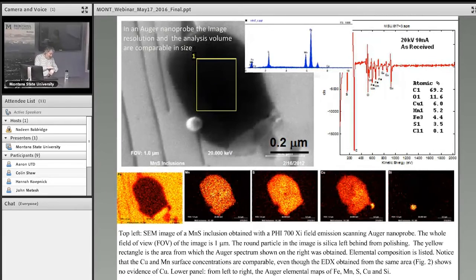Here is a polished surface, and we take an EDX spectrum from here. The EDX tells me it's a manganese sulfide, and there's some iron because it's inside an iron matrix. And there's this nanoparticle. We don't know what it is. And now we take Auger from the same location in this yellow square. Wow, we see copper in addition to everything that EDX said. I never knew there was copper there. We've been working with this sample for 2 years. In the life of me, I wouldn't have imagined there was copper there.